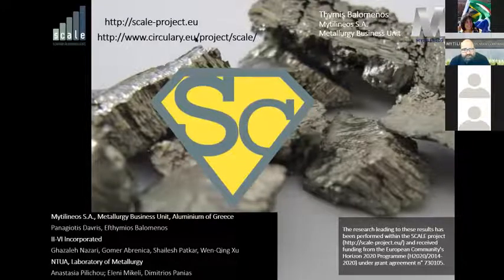Rarely will you get a rare earth reading on an XRF. Maybe perhaps some cerium, but you will not be able to see the other ones. So you need to do a fusion and a leaching, a fusion and an ICP measurement. You don't get a lot of problems if you do that. You will find this above 50 ppm, so it's not a problem. Oh, okay. I hope, Carol, you have been answered there.